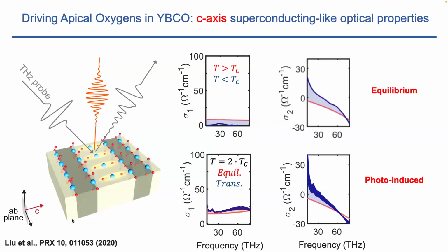Okay, so now let's take this material, YBCO. You pump it. The mode you decide to pump is this mode; these are the superconducting planes in the AB axis, and this is the C axis. What we focused on was a specific mode in which the position of the apical oxygen is modulated backwards and forwards, and the distance of the apical oxygen to the superconducting planes is modulated.